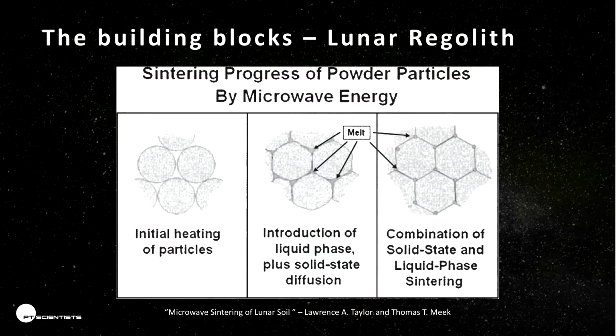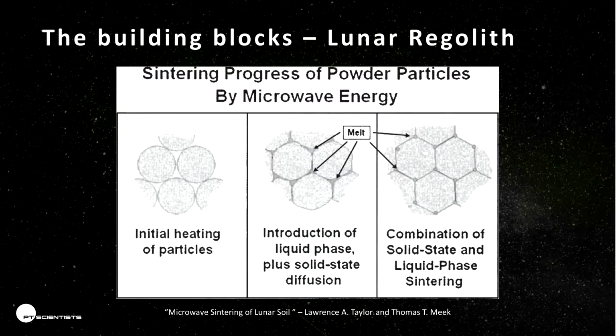But there is one interesting property that is known for some of the Apollo 11 and Apollo 17 samples, and this is that it contains some iron. You can see those little bits of elemental iron enclosed in the glass. This absorbs the microwave energy very efficiently, so with very little energy, you can get a liquid phase between the particles, which then heats up even more, and there is a runaway thermal reaction so that you get a solid material after you bombard it with microwaves.